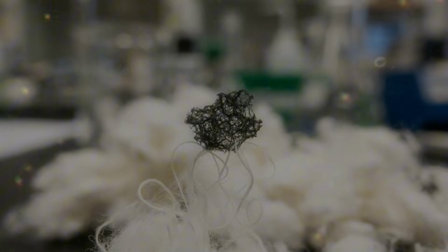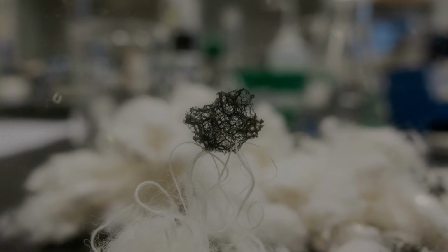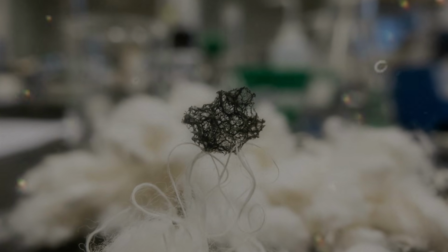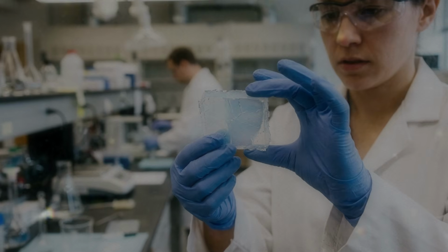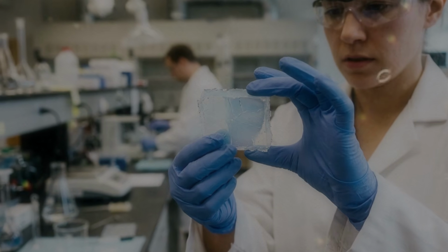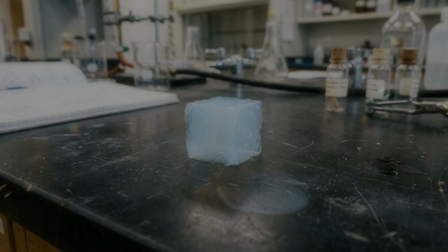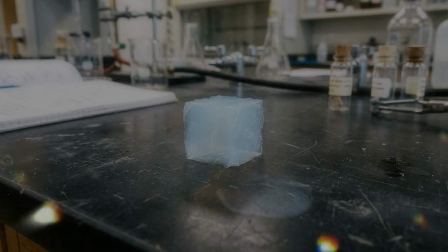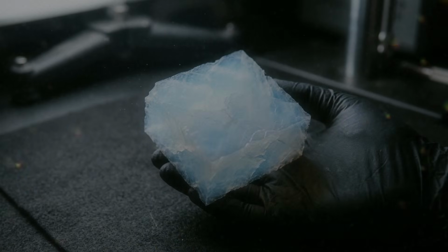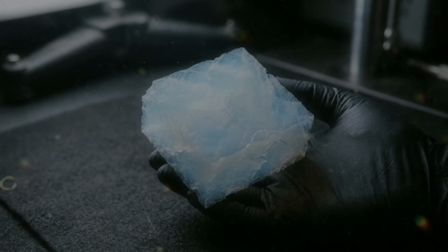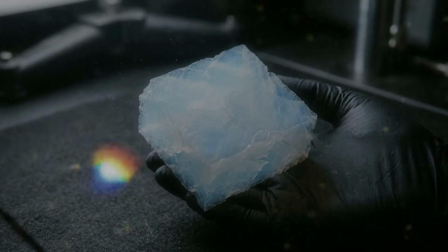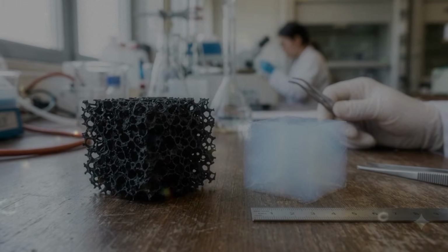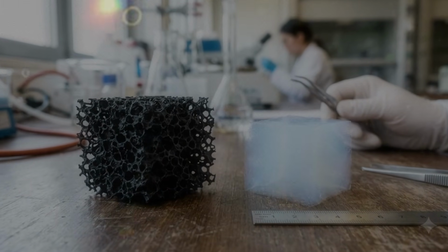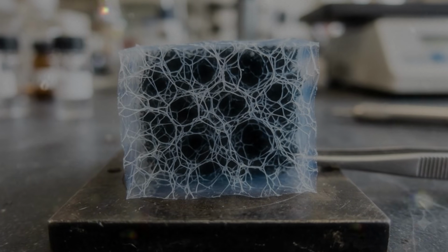Graphene aerogel has a different appearance. Its framework is usually formed from thin carbon-based sheets that fold, wrinkle, overlap, and connect. Some regions may look like crumpled paper. Others resemble the walls of an irregular sponge. The sheets can bridge across open spaces, bend around pores, and meet at junctions where force and electricity move from one part of the material to another. Those junctions matter more than the amount of material alone. A network can contain strong building blocks and still behave weakly if those building blocks are poorly connected.